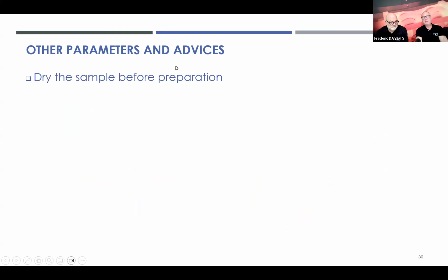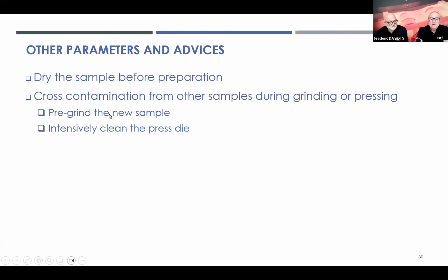So some other parameters and some advice to make pressed pellets. Dry the sample always before preparation, because liquid is simply not a part of your sample. We cannot analyze it, at least with XRF. It may be part of your sample when it is, for example, hygroscopic water or crystal water. But we should dry the sample.